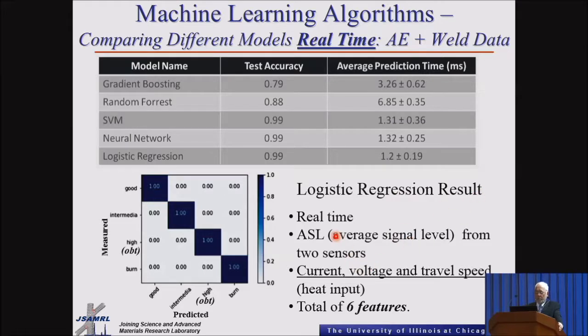Also, remember that we said we were testing the UT, but the UT is post-weld. It is not done at the same time. It comes after the weld has been solidifying. So we looked at the acoustic emission and just the weld data, pretty much to take a look at the actual real-time welding. We took the two sensors from the average signal level, the current, the voltage, and the travel speed, which gave us a total of 6 features. And you can see the correlation was pretty good, with good agreement between the measured and the predicted value.